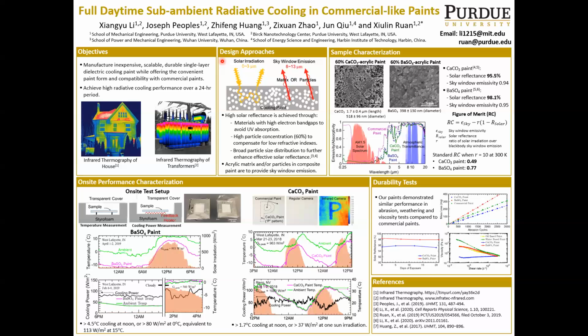Although there are many studies on radiative cooling coatings, most of them are not in a paint format or require high coating thickness. Commercial white paints are often limited to around 90% solar reflectance, not sufficient for full daytime radiative cooling. This schematic of the cooling paints shows that particles are responsible to provide solar reflectance, while both matrix and particles can provide the sky window emission.